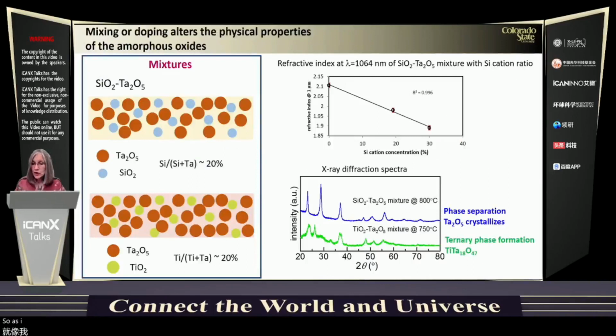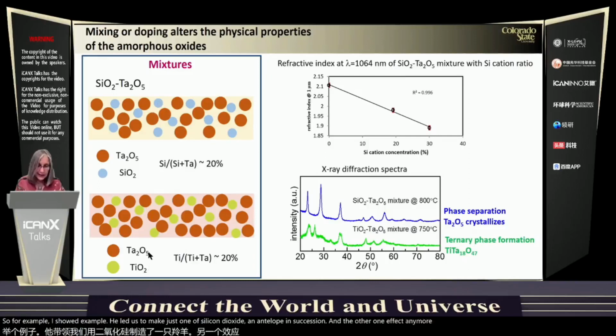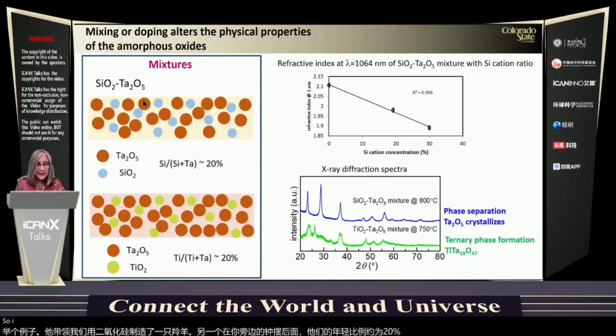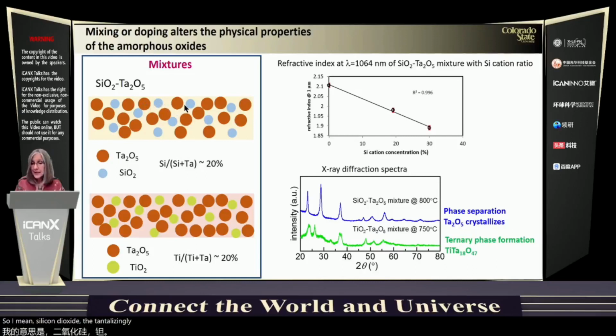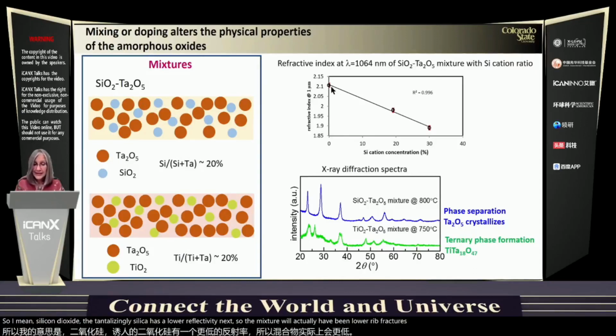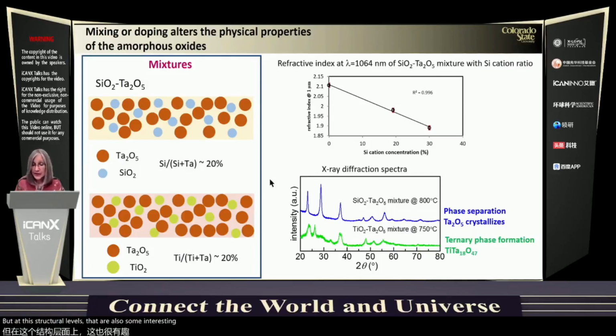So as I mentioned, we can also grow mixtures. And what mixtures do is they alter the optical and structural properties of the oxides. For example, I show here 2 mixtures, one of silicon dioxide and tantalum pentoxide, and the other of titanium dioxide and tantalum pentoxide, with a cation ratio of about 20%. Adding silicon dioxide to tantala, silica has a lower refractive index, so the mixtures will actually have a lower refractive index than pure tantala.